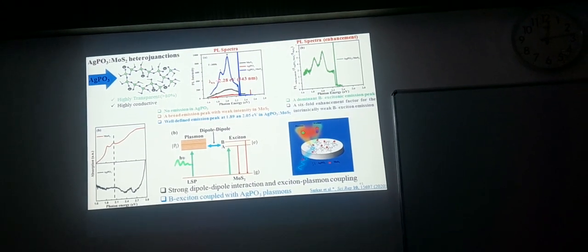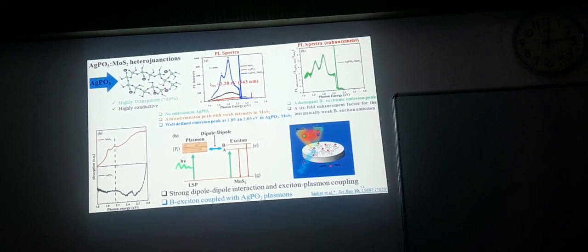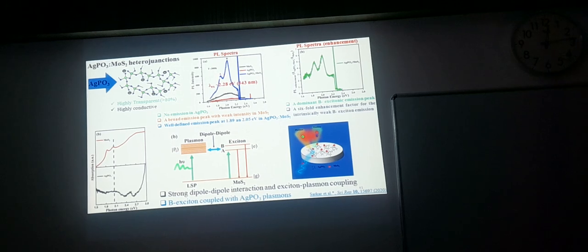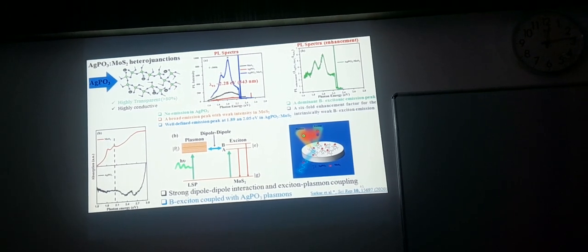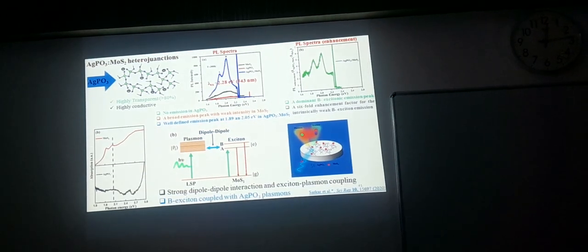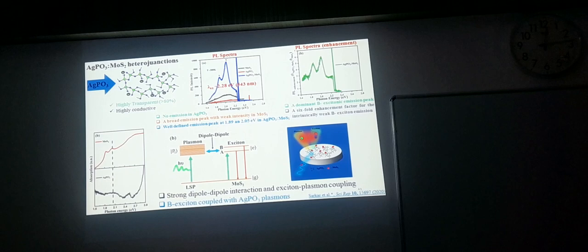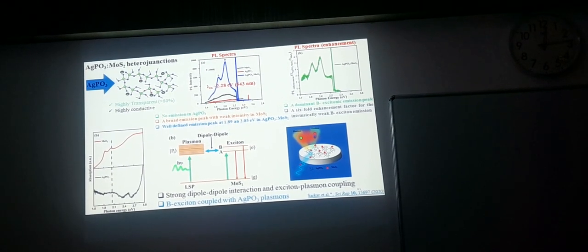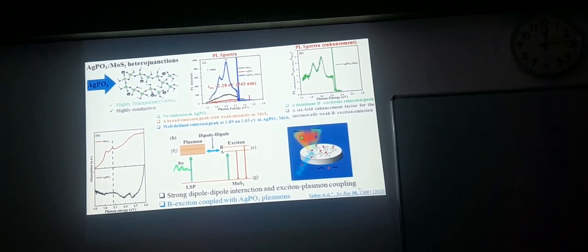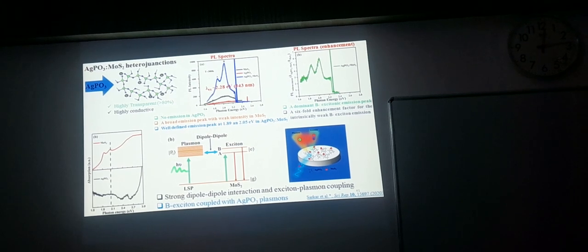So here we studied the fundamental science. You can see here that the A exciton is basically diminished. If you look here, the A exciton is the dominating one, but the B exciton is not. So in this case, we studied how you can tune the B exciton in the presence of this silver phosphate, and we were able to understand the dipole-dipole interaction.